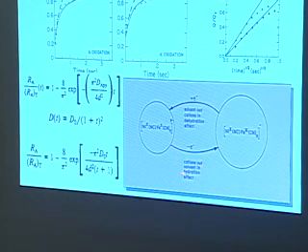Now, I will not presumably see the solvent coming in as a dynamically limiting event, because there's 55 molar water out there, and it will come in, and it's already there, and so I'm never going to pick that up. That's going to happen way too fast. I'm not going to pick up the hydration of the cation as a limiting event, because the cation shoots out of the surface, it's out in water, and it hydrates at its own time scale, and I can't see that because I'm not doing any redox chemistry.